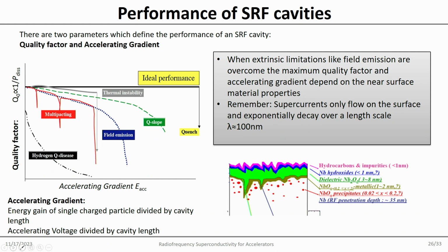So, if we look at this niobium surface, you will see it will not look on the nanometer scale like a very clean metal. No, we have hydrocarbons, we have different niobium oxides, and they really have very different properties. Some are weak superconductors, some others are normal conductors, others are dielectrics, and you got some of the niobium oxide going in as precipitates into the deeper layers. So this is how a realistic niobium surface could look.